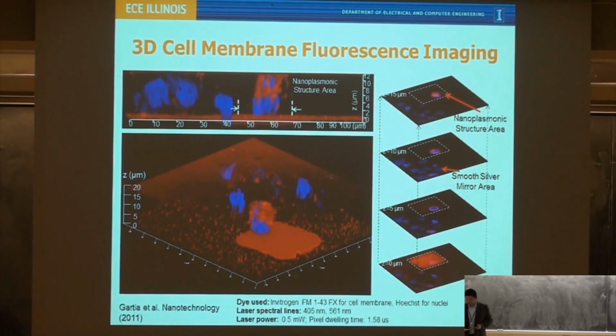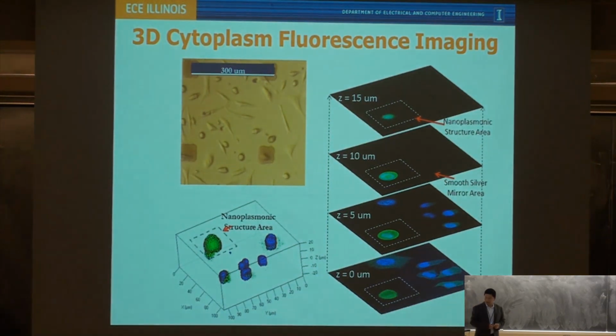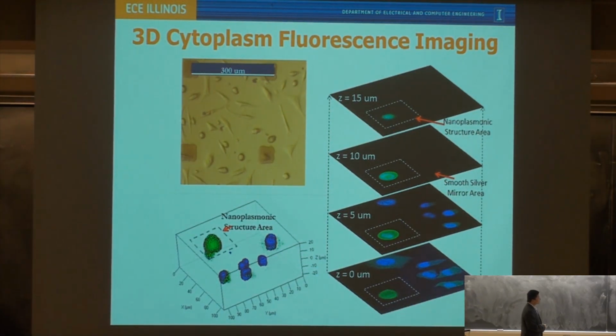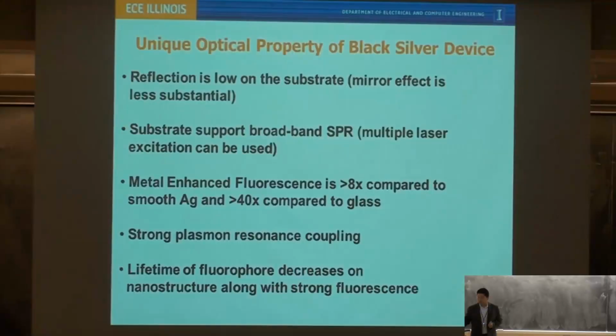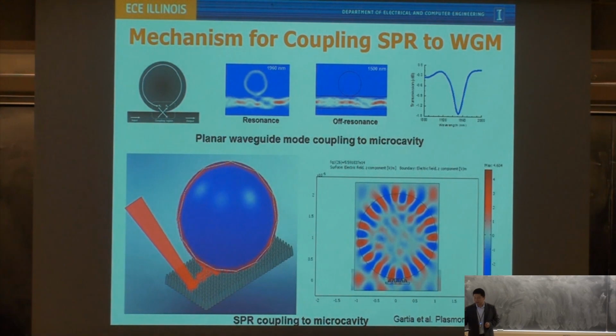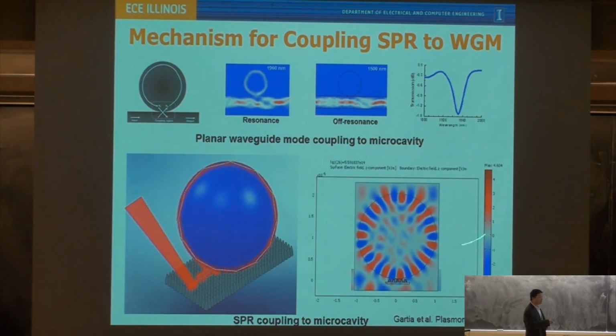We also did the other dye to label the calcium inside the cells. Now we're not labeling the cell membrane but labeling the cytosol. We are actually labeling the calcium in the cytosol, and then also labeling the nuclei with Hoechst dye. We see a very similar effect: when the cell is sitting inside these small squares, the cytosol fluorescence becomes much brighter. But we don't see a lot of difference in the nuclei fluorescence intensity. That triggered us to think about the mechanism: most of the light energy is concentrated or enhanced around the cell membrane, so you don't have a lot of enhancement inside, in the center of the cells.